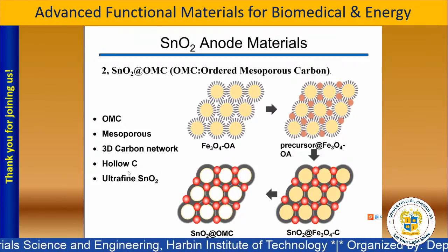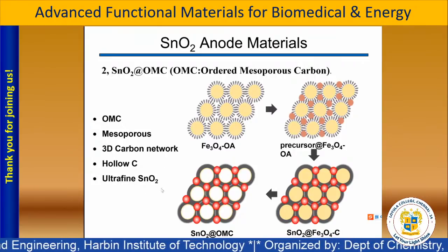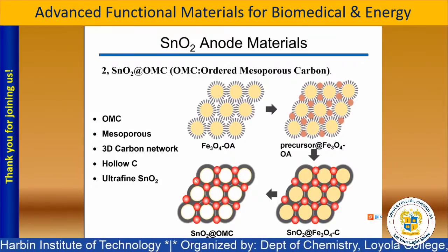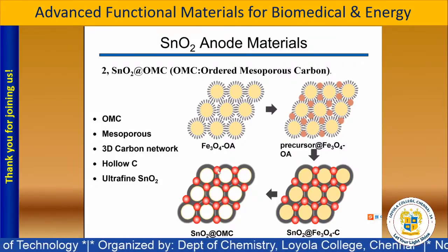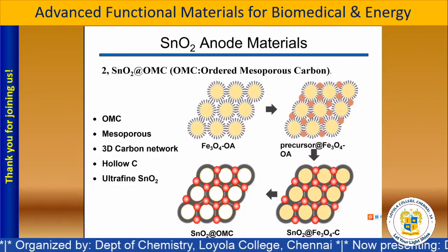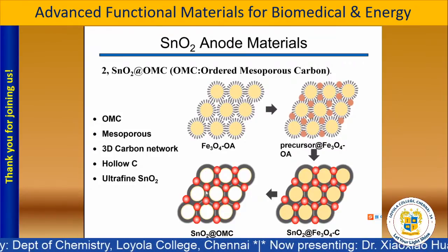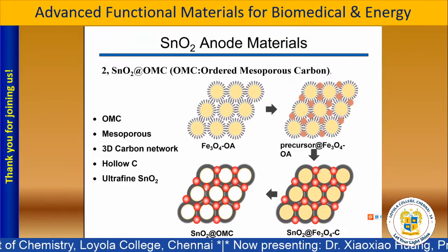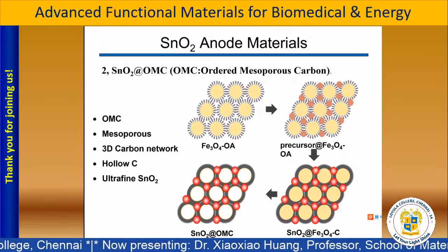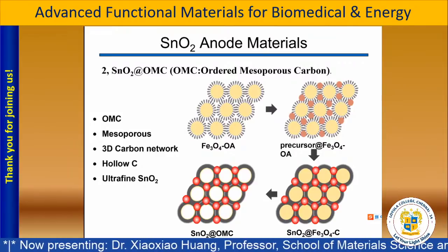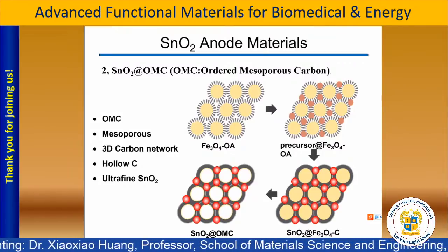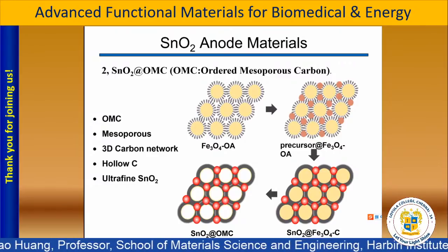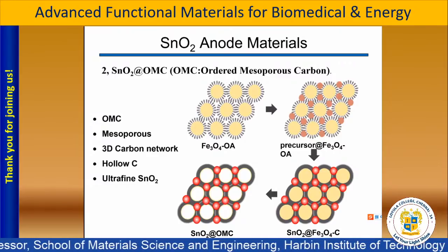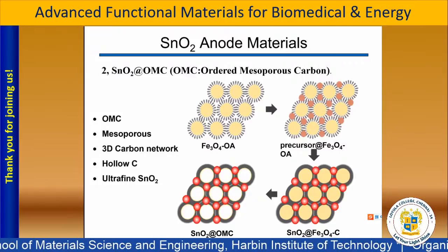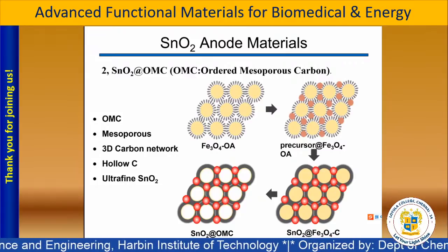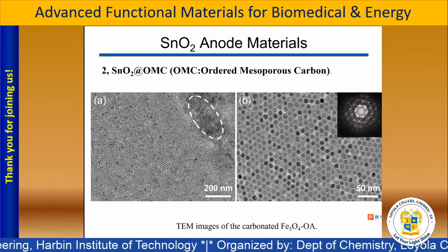And the last one, and the most important, is that we can get the ultrafine tin oxide. The ultrafine tin oxide and the OMC structure not only shorten the diffusion distance of the lithium ion, but also decrease the polarization, both of which can be helpful for the properties. So we designed this material and we got it.